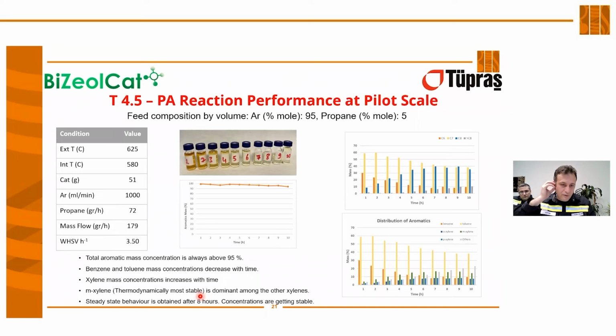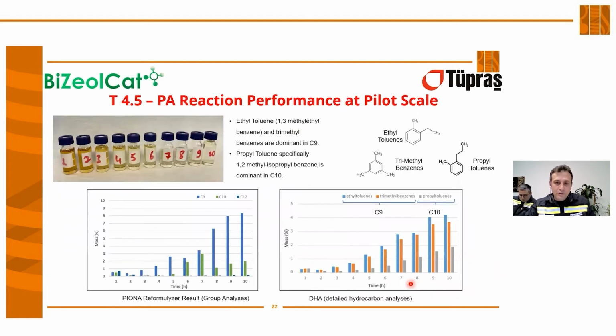We obtained a steady state behavior at 8 hours, and concentrations stabilize after this point. When we look in detail at the C9 and C10 hydrocarbons, we find ethyl toluenes and trimethylbenzenes mostly in the liquids, and also some propyl toluenes in the C10 fraction.